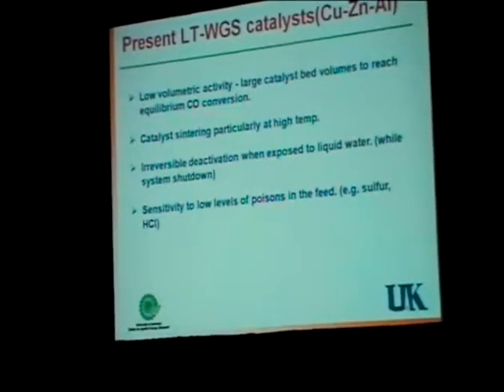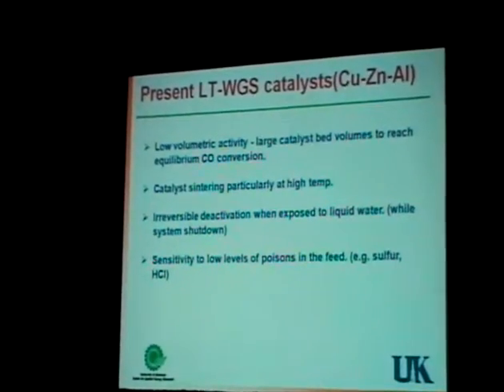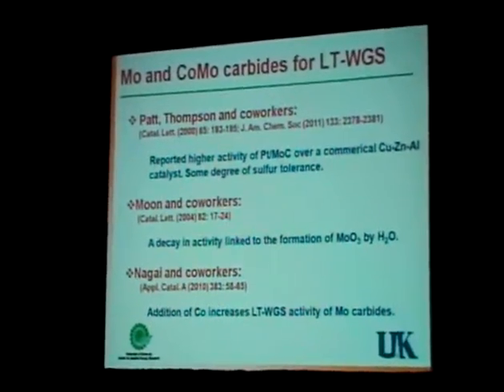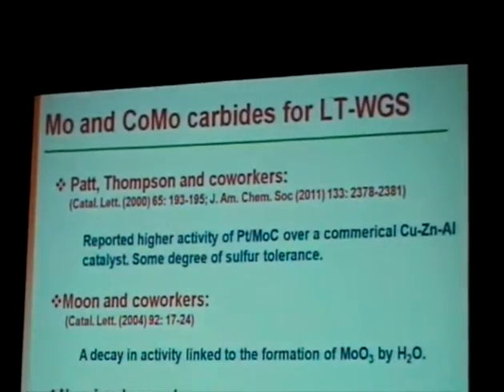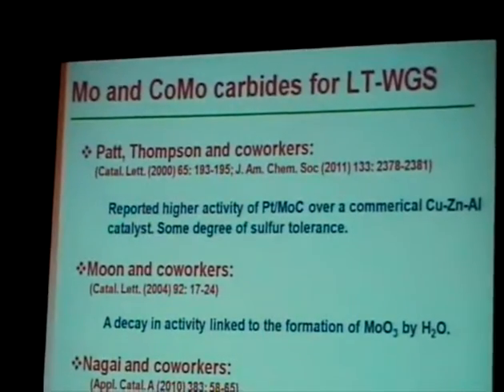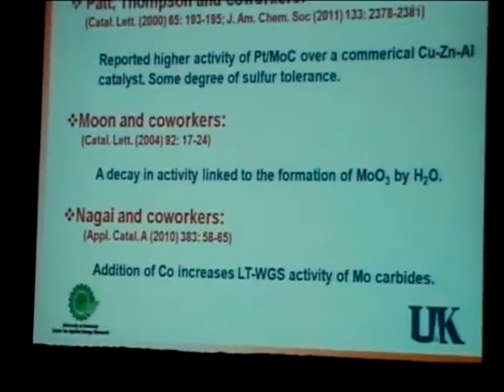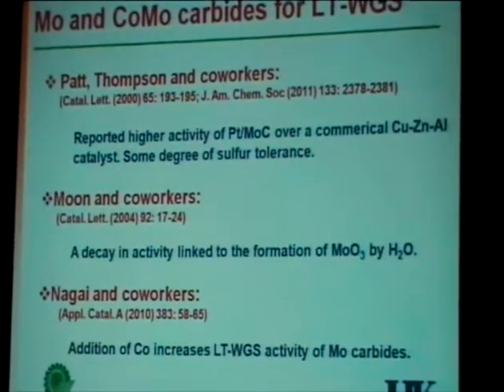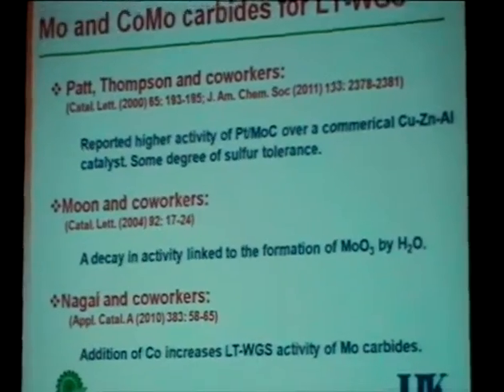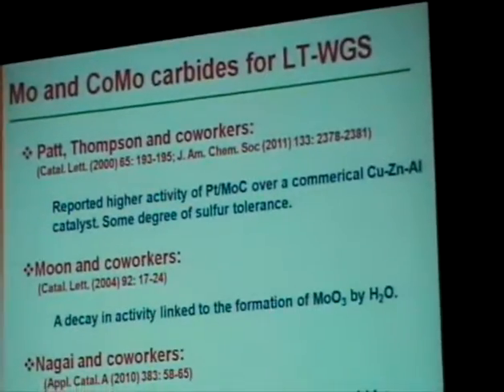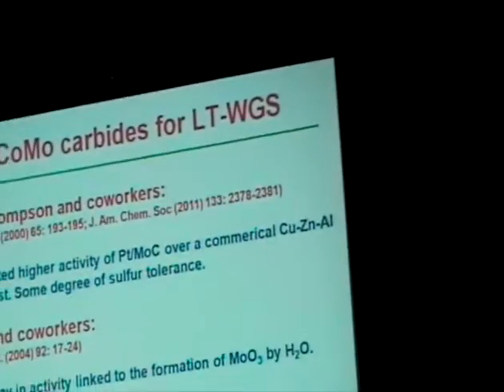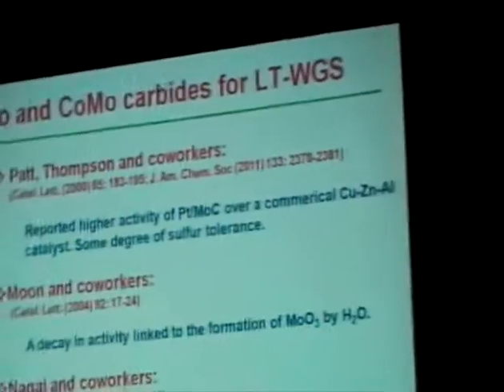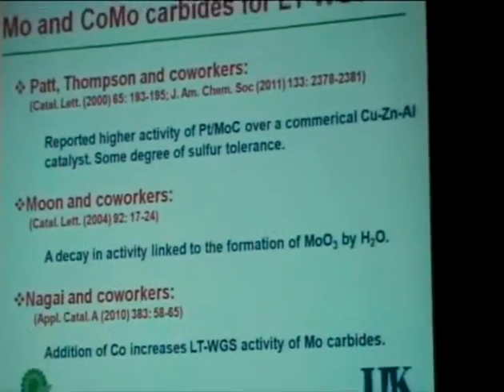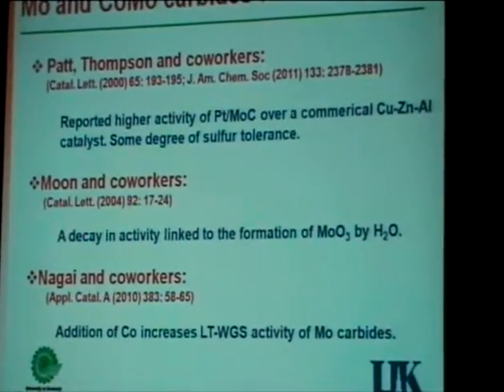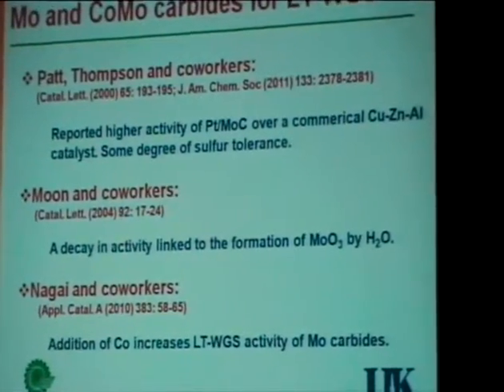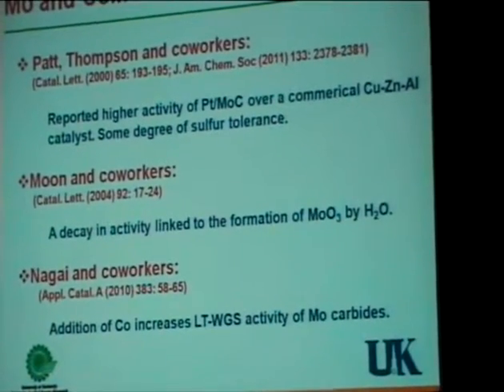So in order to look for an alternative water gas shift catalyst, Patt, Thompson and coworkers recently published work on molybdenum carbide catalysts, and they've shown higher activity compared to copper zinc under standard conditions. And to some degree the catalyst showed sulfur tolerance compared to the copper zinc catalyst. And Moon and coworkers also published work on molybdenum carbide, and they've shown that the molybdenum carbide is not stable for a longer period of time, and it could deactivate by the presence of water.